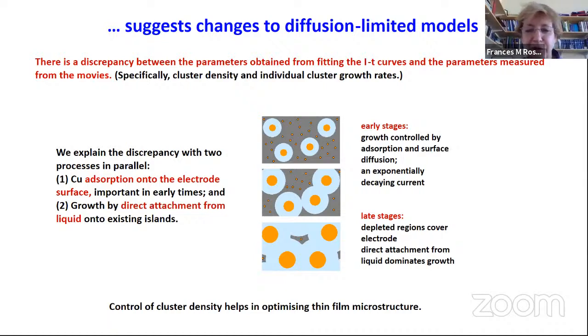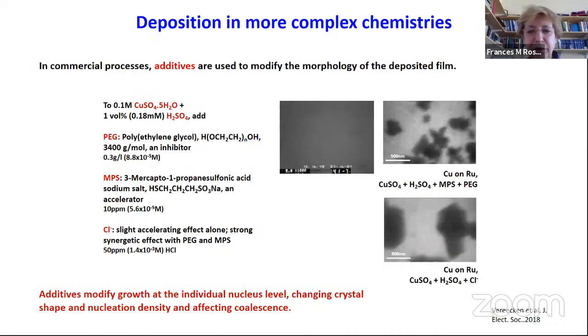They have to arrive on the electrode, and then they have to diffuse laterally to arrive at a nucleus, and those processes have different diffusion parameters, and therefore you can expect different kinetics compared to a model that imposes a single diffusion parameter. Okay. All right, so you can go further with these kinds of deposition experiments,